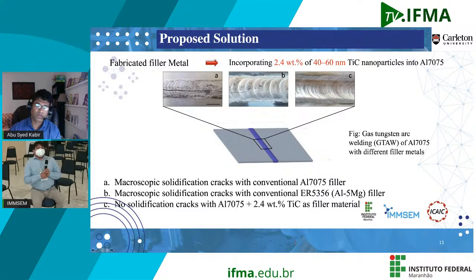And the image shows the output of the welding process. You see a big solidification crack right in the middle on the first image when they use 7075 filler metal. There's a big solidification crack when you use the aluminum 5% magnesium. But look at this one, 2.4% titanium carbide nanoparticle infused 7075 filler metal. Absolutely no cracks at all. So they were able to eliminate the solidification crack entirely by the use of 2.4% titanium carbide nanoparticles.